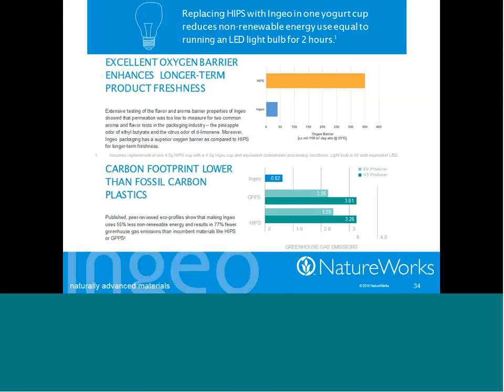And then, this is something that we would have led with in our early days, but now only after delivering on price and performance do we mention that Ingeo comes with a lower carbon footprint. In comparison to polystyrene, we use less energy to actually make the polymer itself, and we consume a significant amount of greenhouse gas in the production of the monomer, and therefore the polymer.